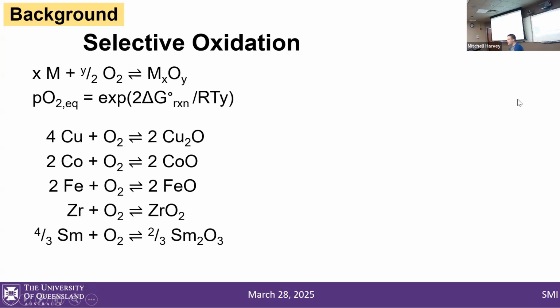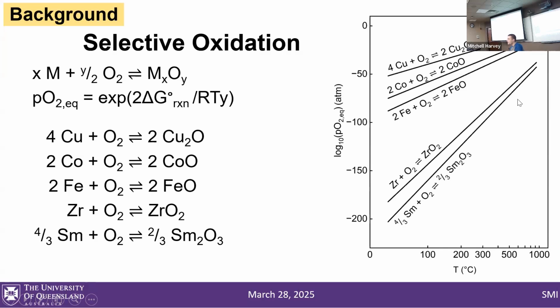So if we take all our possible reactions for the pure metals in the samarium cobalt magnets, we can use this thermodynamic data and this equation to calculate the oxygen partial pressure for each of these metals. And so then we can draw some arbitrary line. Let's just say we have this line, and we're going to control the PO2, the oxygen partial pressure, along this line, along this temperature range.